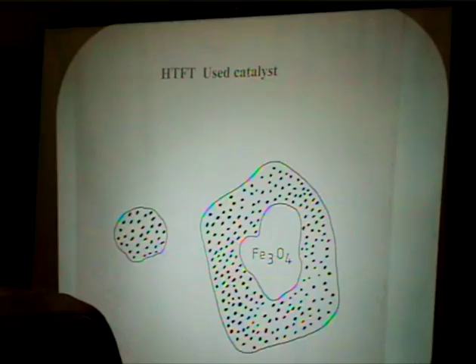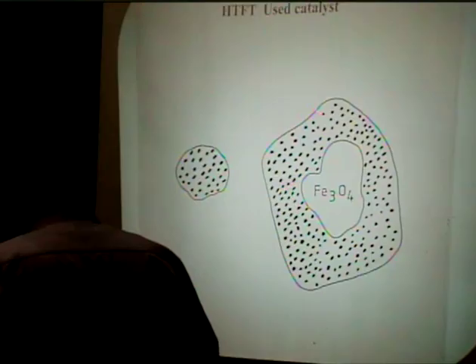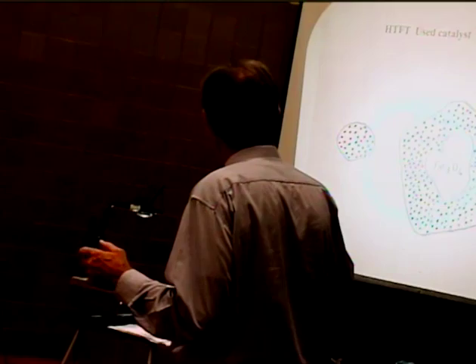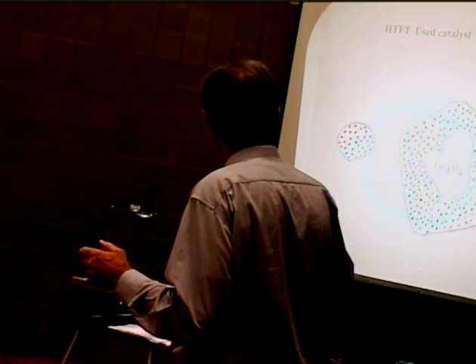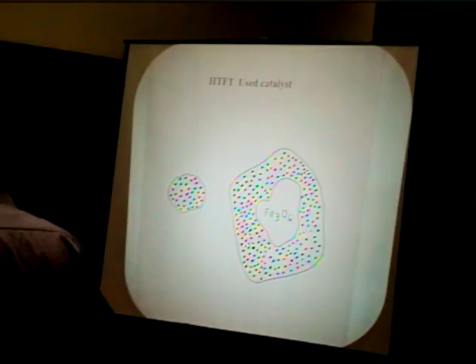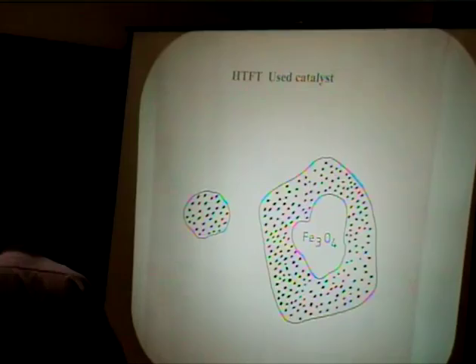This raises the question of why bother with 100% reduction. We deliberately took fused iron and reduced it stepwise — 10%, 20%, 40% and so on — and found that activity increased with degree of reduction up to around 40-60%, after which it flattened out. There is no point in reducing to very high levels. Coming back to the apparently declining activity in the circulating fluidised bed: as you deposit carbon, you get abrasion, the material chips away, becomes weaker, breaks up, and the finer, carbon-rich and alkali-rich particles are blown out of the system. Despite cyclone efficiency of 99.99%, you still continuously lose alkali-rich fines. Because of this you lose alkali and lose the carbon-rich part, and by difference the remaining material appears oxide-rich. It is simply because you are losing carbon-rich material that the balance becomes apparently oxide-rich — not true progressive oxidation.